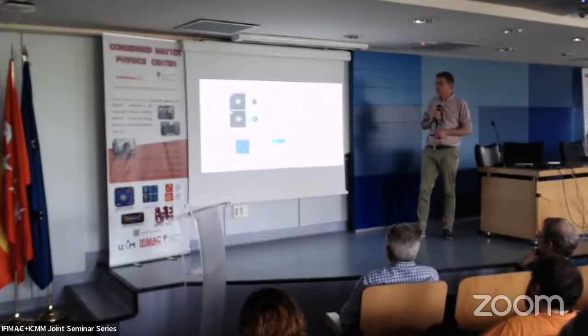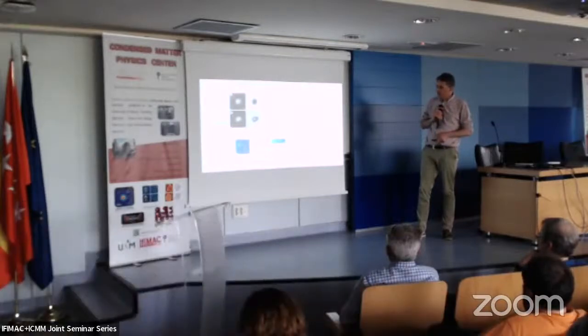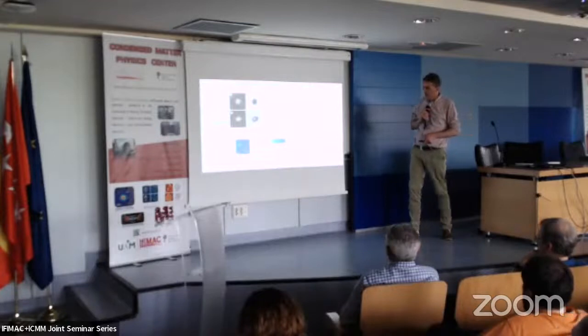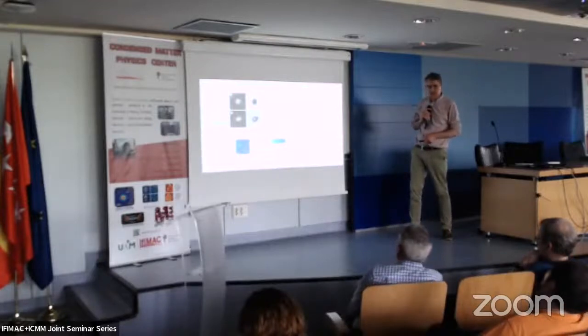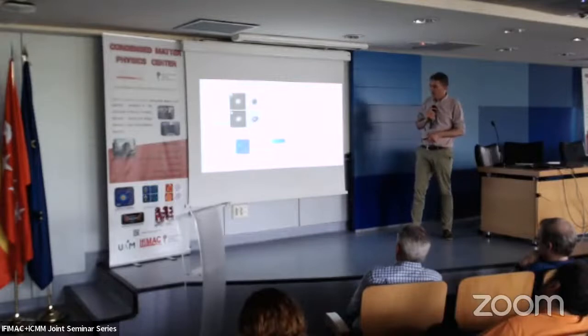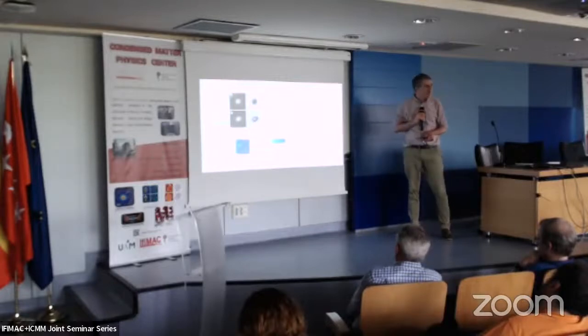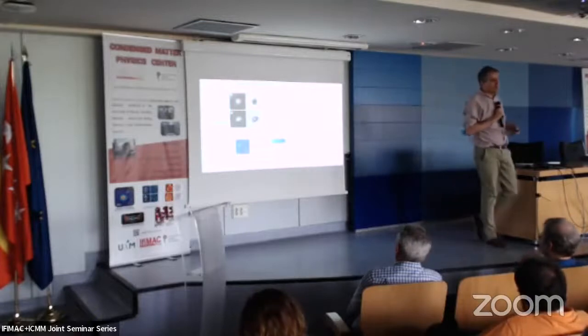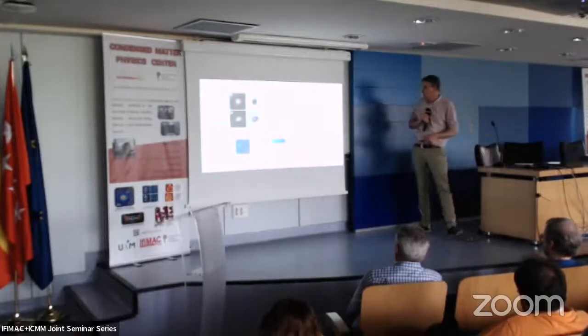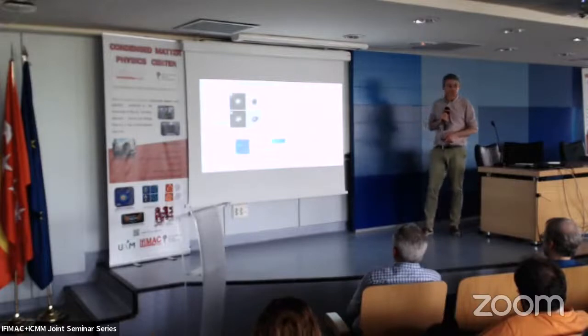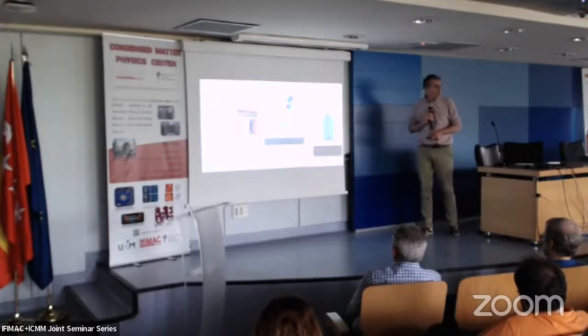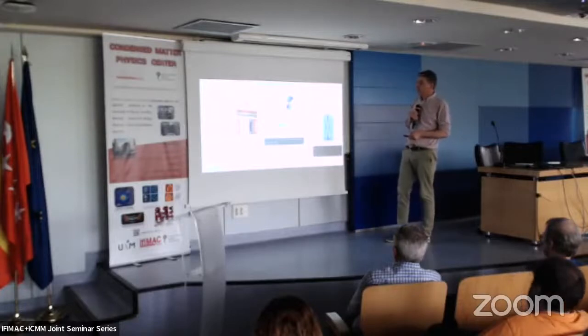People showed that when you have this exchange interaction, you immediately see a very strong electron-hole asymmetry. And this is something which you can understand theoretically. And you see here peaks inside the superconducting gap, and you see that these peaks are located differently. There is a high peak here at negative bias, and there is nothing at positive bias. And when you plot this density of states as a function of the position, you see oscillations. These oscillations give you a length scale, which is the Fermi wavelength. And you can follow these oscillations and follow the physics which is behind these localized states. Of course, as said by Juanjo this morning, you can follow these states as a function of the position, and you can see where you find Majorana fermions.